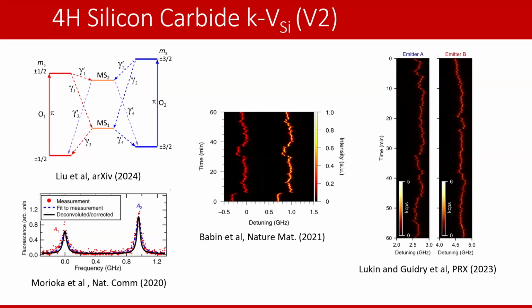Additionally, because it's in silicon carbide and the location of the missing silicon atom in the V2 center is at the K site on silicon carbide, it's not inversion symmetric, which means that it is sensitive to first order electric fields, unlike some of the diamond defects, which are inversion symmetric, which protects them from this first order electric field. And what that means is that for a long time, people believed that you would not be able to have stable defects within silicon carbide, stable optical lines, because the movement of charges within the silicon carbide itself will cause spectral diffusion and spectral wandering.